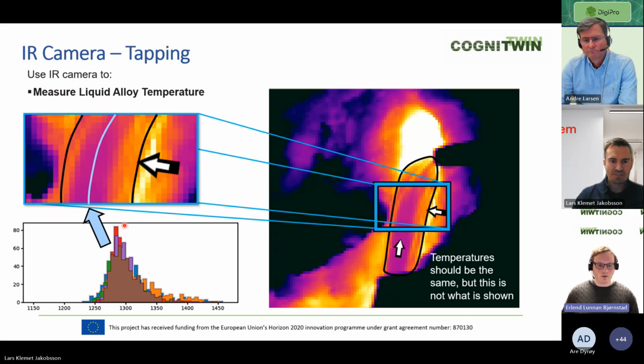But what we found was that if we managed to follow a consistent streamline in that jet using our different algorithms, then we get this histogram that we can see here, which follows different points along this blue line, where we can get out a consistent temperature. So here the temperatures are uncalibrated, but you can at least see the consistency.